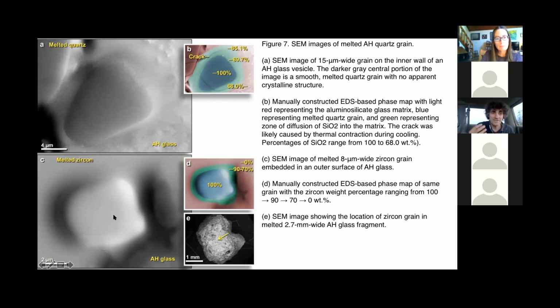And here, zircon, right? A lot of you may have zirconium fake diamonds, right? So this is zirconium that you can see. If you were in this village and had this zirconium diamond, it could have melted, because this is actually zirconium, like 100%. And then as soon as you go away from the zirconium, you can see how it's dissolving. So it's evident that the zirconium was completely molten in this Abu Hureyra glass.